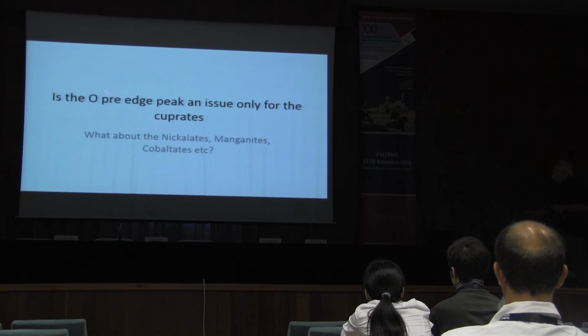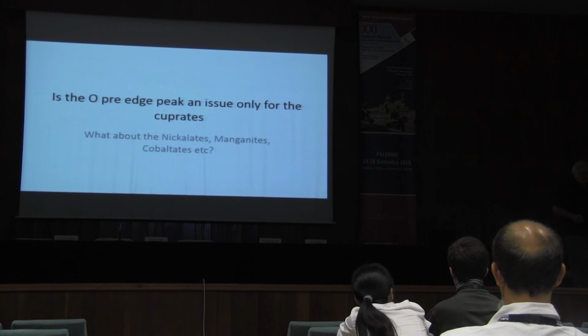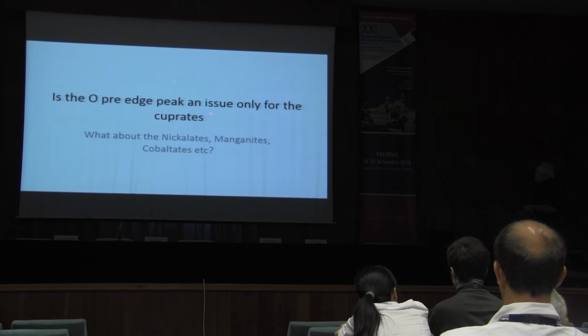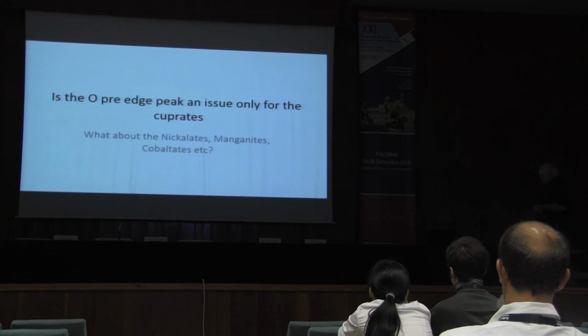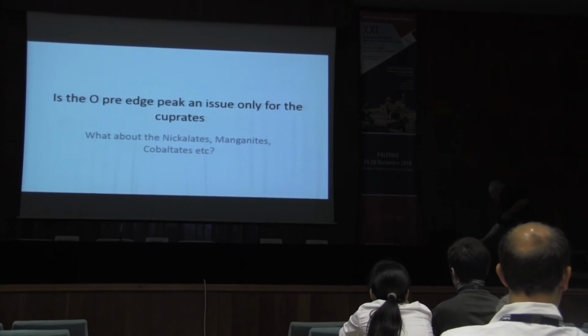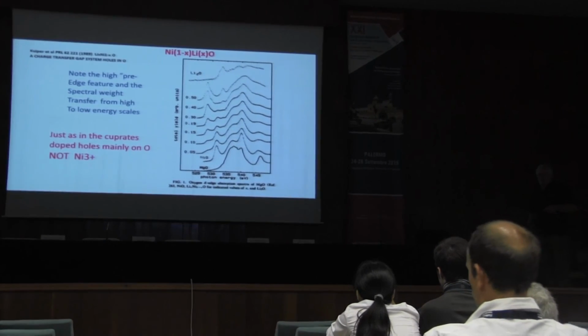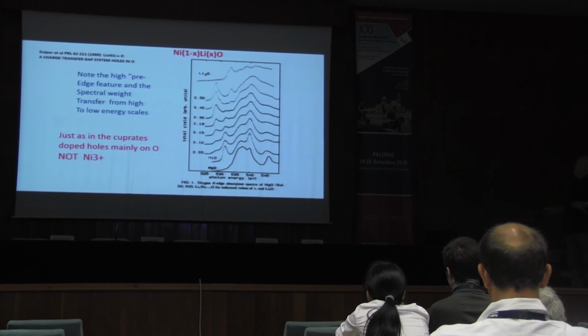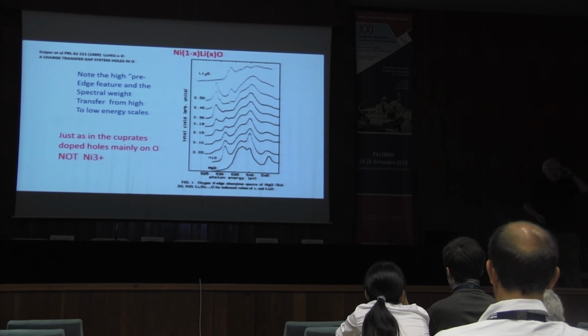Okay, now is this oxygen pre-peak that we see in X-ray absorption, which was the thing that told us that maybe we should have a different starting point, don't think of copper 3+ so much, but think of copper 2+ and a hole on oxygen when you dope the material. Is that an issue only for the cuprates or also for other materials? Well, let me show you. So here is lithium substituted nickel oxide. You know, this is the battery material, right? So it's a very important material, actually.